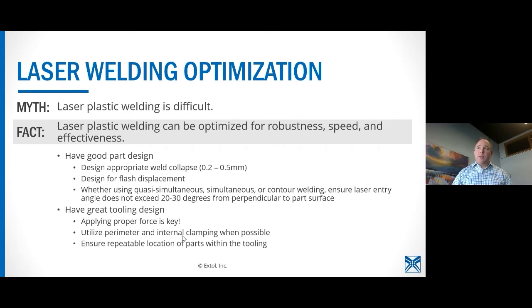What I will say is we have a closed loop weld depth parameter. We have different weld modes within our welding system, so a number of passes, but what we typically see is we press the parts together, make sure that intimate contact is consistent before we even start the weld process, and then we start to apply the energy to the weld rib and watch that collapse as it occurs. And what happens is we see a very consistent weld time to hit that depth. So our control system has parameters around both the weld depth, an upper limit and a lower limit, which is typically done at start of production DOE by our customers, or we can control the weld time. So that if for some reason it's taking too long to get to that depth, we see that as well.